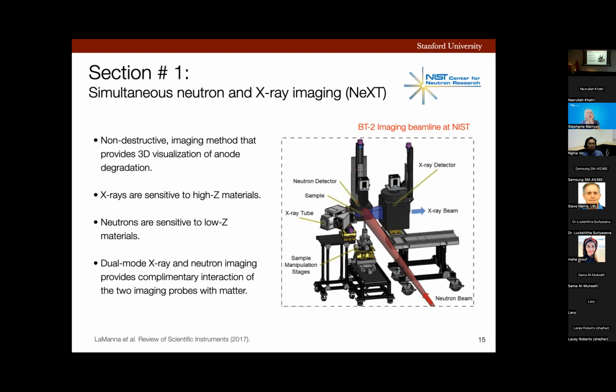In this schematic, you can see that red is the neutron beam, which is produced by a nuclear reactor. Blue is the X-ray beam, which is produced by a microfocused laboratory-based X-ray source. Now, these two beams hit the sample at the same time during the imaging experiment, and they are perpendicular to each other. And then we have a neutron and an X-ray detector that detects the neutrons and X-rays after they have interacted with the sample, providing us a neutron and an X-ray image.